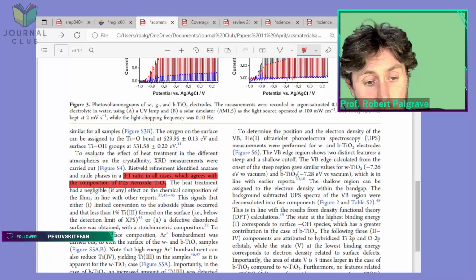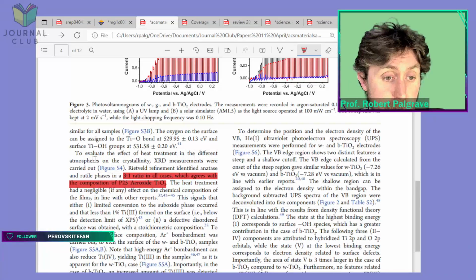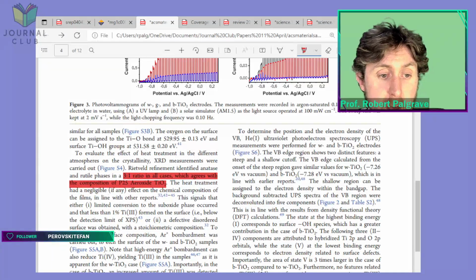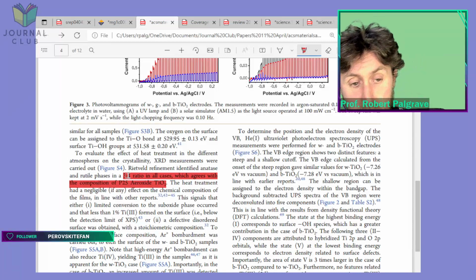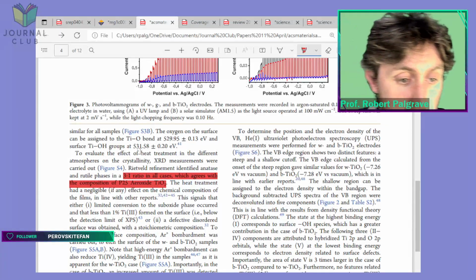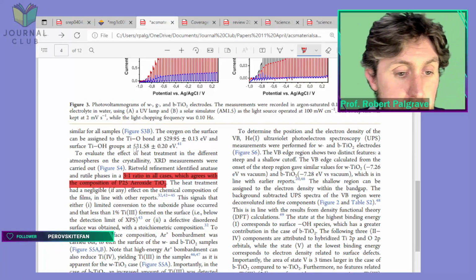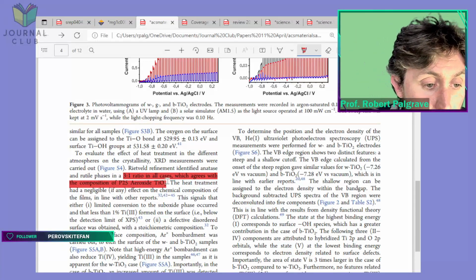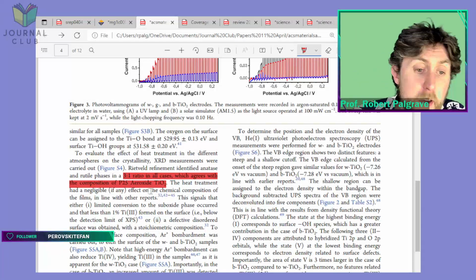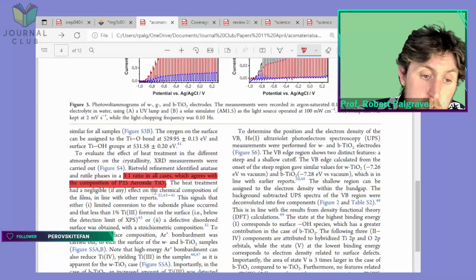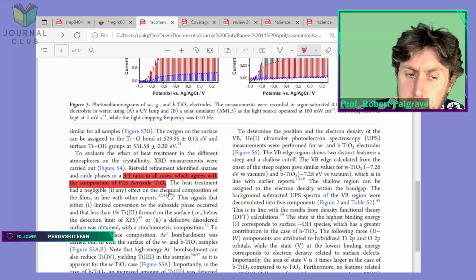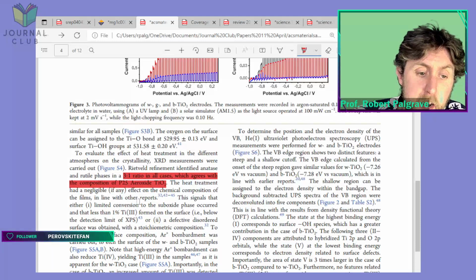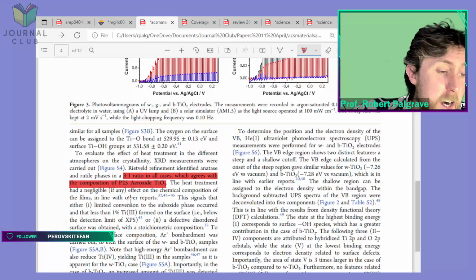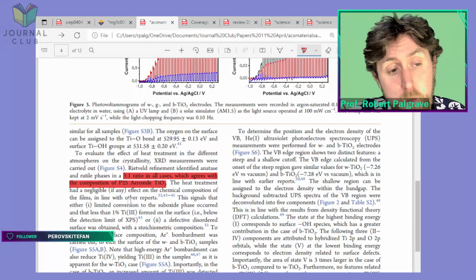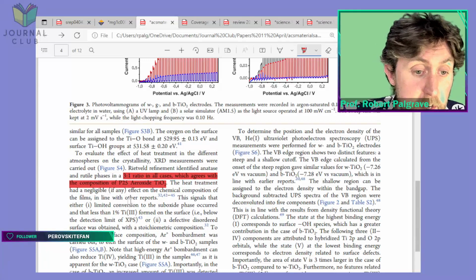and an example here, you can use it to understand phase fractions, which I've done, and they got a not particularly surprising result, which was a 3:1 ratio, which I think is probably what it said on the side of the bottle of P25, but it's always good to confirm that. So the heat treatment had negligible, if any, effect on the chemical composition of the films. Maybe they mean structural composition, maybe they mean the phase composition, I would say, in line with other reports. So yeah, if you heat up anatase TiO2, it will eventually change into rutile TiO2.